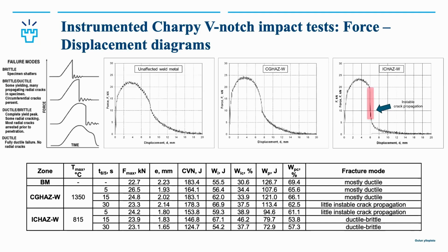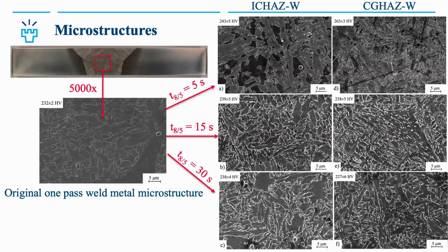And then we'll move on to microstructures. This is the original unaffected weld metal. Microstructure consists of acicular ferrite mainly, but there is also grain boundary ferrite and ferrite side plates are also present. And then these images show the intercritical heat affected zone and coarse-grained heat affected zone with different cooling times: 5 seconds, 15 seconds, 30 seconds.